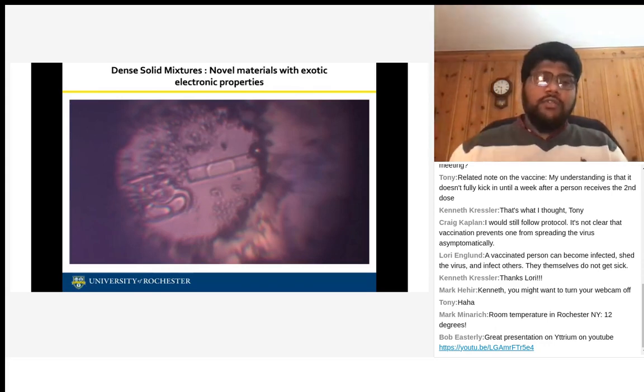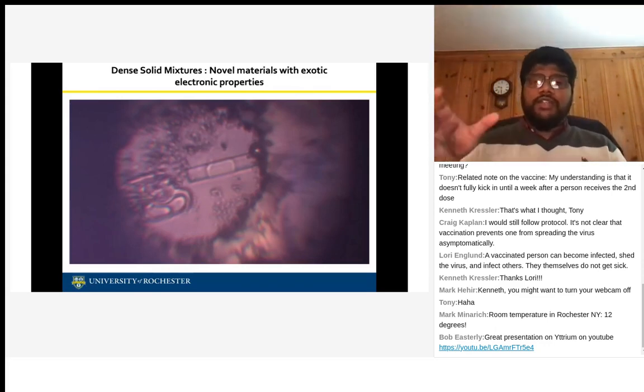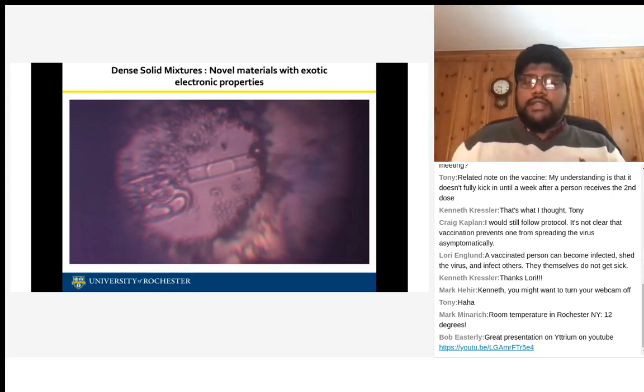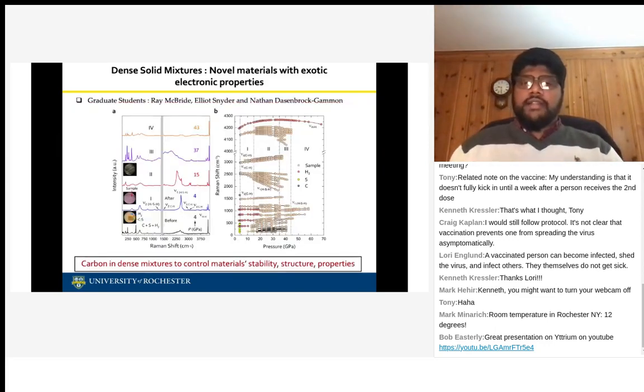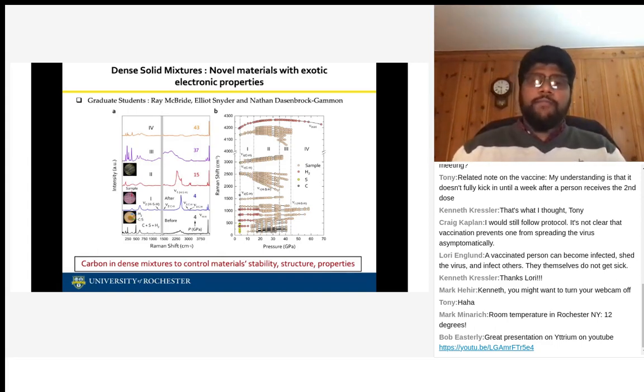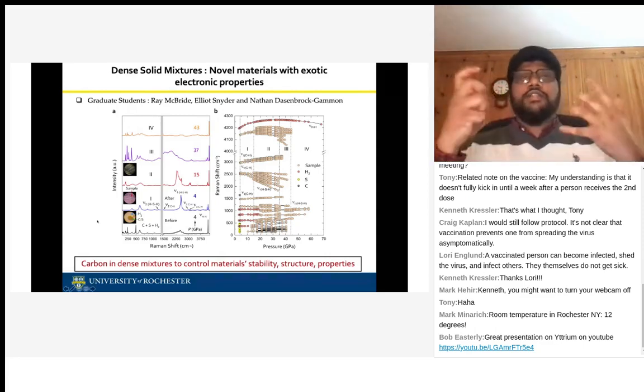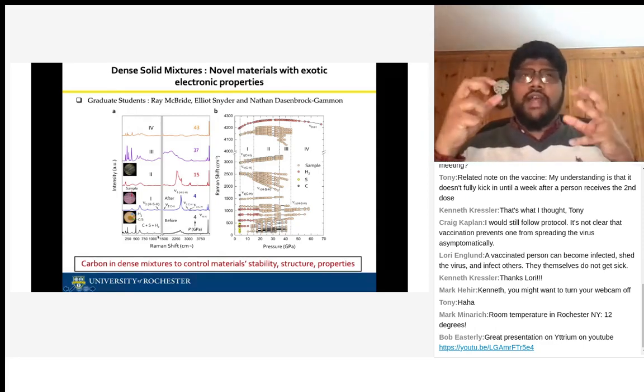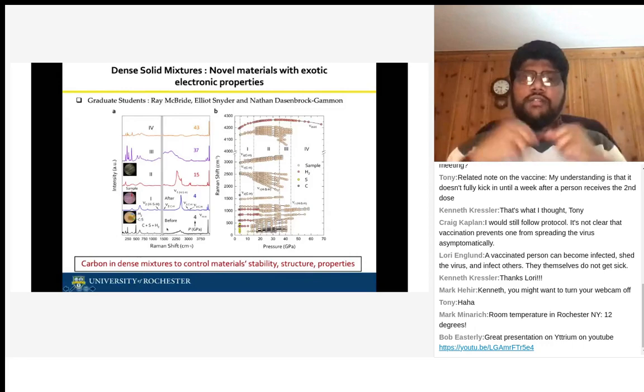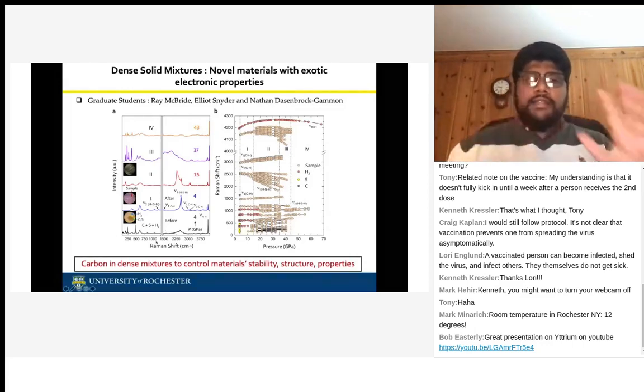So by adding carbon into the system, we were able to successfully get the right conditions that favor high Tc superconductivity. To prove this material is superconducting, what we did was study Raman, electrical resistance, and magnetic properties. What you're seeing here is the Raman spectrum of this new material, which tells you what kind of bonds and what kind of vibrations this material has.